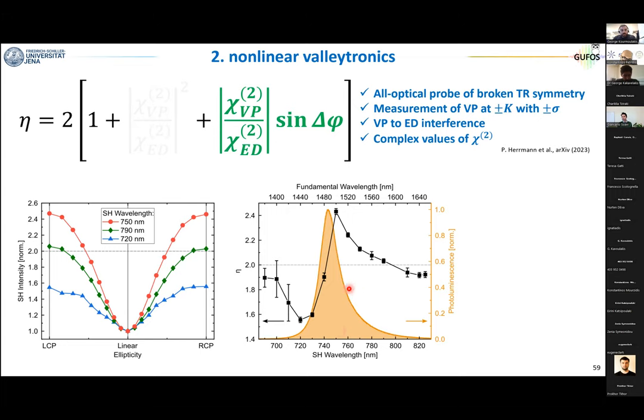I find this very beautiful for several reasons. First one, this is a method that allows us to probe directly broken time reversal symmetry in TMDs while being perfectly selective with the valleys, because now we can really shine circularly polarized light and measure the nonlinear response. But to the best of my knowledge, this is also the very first demonstration of interference between broken space inversion symmetry and broken time reversal symmetry in a TMD. That is the analogous of a magnetic field or pseudomagnetic field.